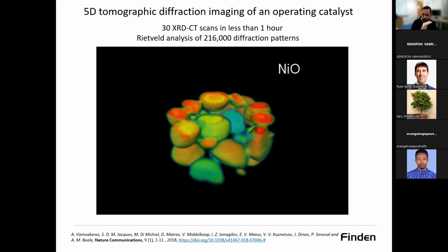That is static, at room temperature, nothing is changing when it comes to chemistry. But you have 3 spatial dimensions, so X, Y, Z, and you also have the scattering, so the chemical information. That means that you can get all this information that you saw for the 2D images, so lattice parameters, crystallite size, in 3D.